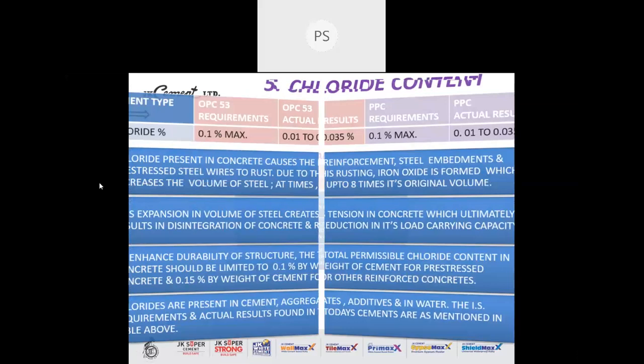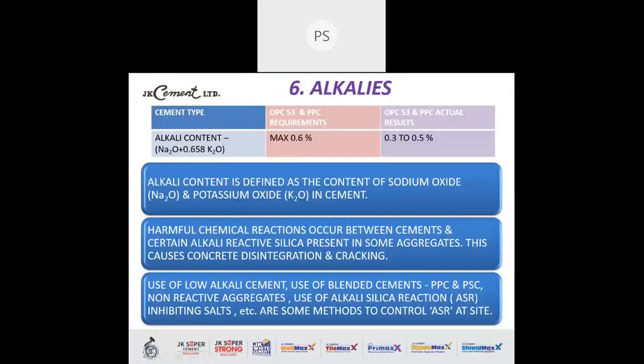Next is the alkali content. Now, alkalis are very, very important in terms of the disintegration they cause in the later stage of concrete life. Alkali content is measured by the formula Na2O plus 0.658 K2O. It should be maximum 0.6% in OPC as well as PPC. In India, we get a range of 0.3 to 0.5% for the alkali content.